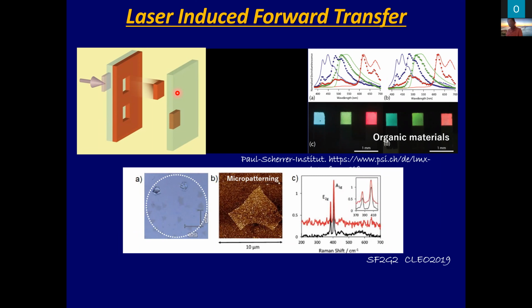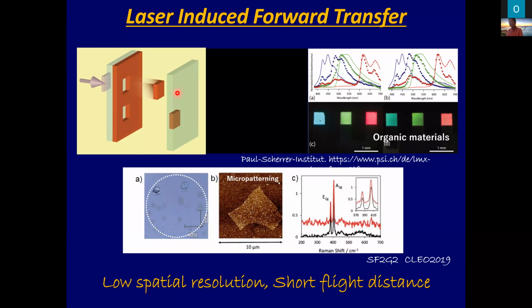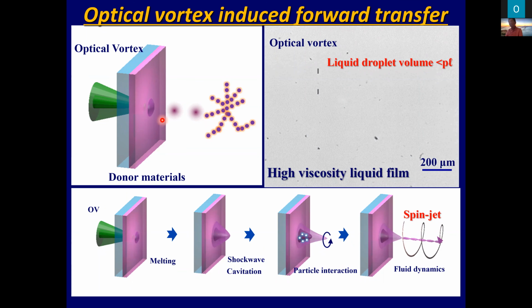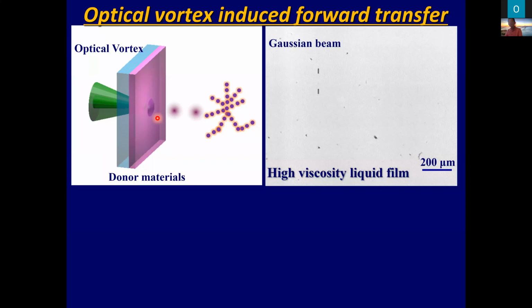We apply optical vortex. The basic concept is quite simple. A donor thin film exists. We pump this donor thin film with the optical vortex. At that moment, orbital angular momentum transfers from the optical field to the donor film. The donor film must be twisted, and it ejects a droplet. The droplet is also spinning. Such a spinning motion can stabilize the straight flight of the droplet itself. We can pattern donor material onto the receiver substrate with high spatial resolution.